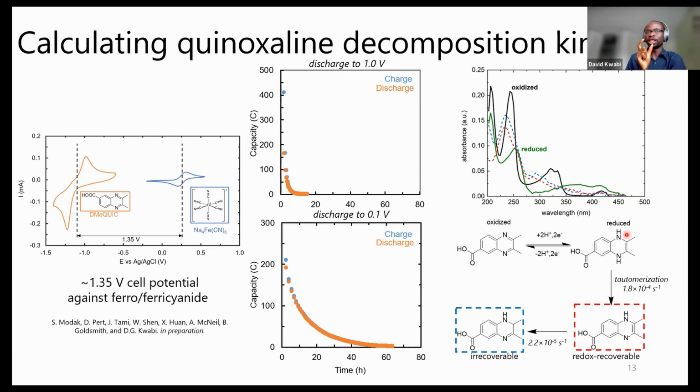We also found a weak correlation with redox potential, which you sort of expect to be the case, right? As that N-H bond is stronger, you're going to have a higher redox potential. So there's a weak correlation between a high redox potential and resistance to tautomerization as well. So those two design rules are at least what I can share that seem to be pointing in the direction of lowering or increasing susceptibility to tautomerization. Thank you. I look forward to reading your paper soon, I hope. Good luck.